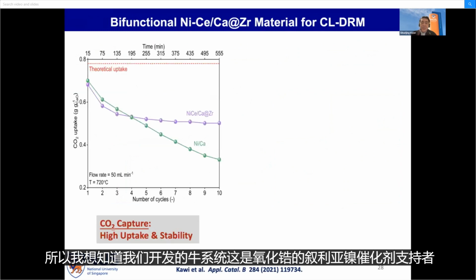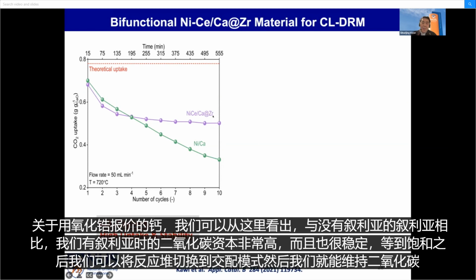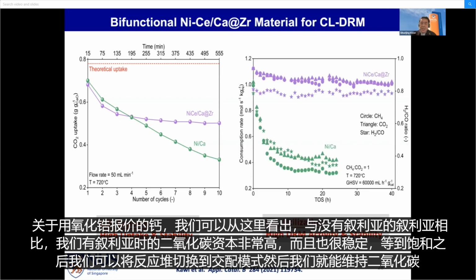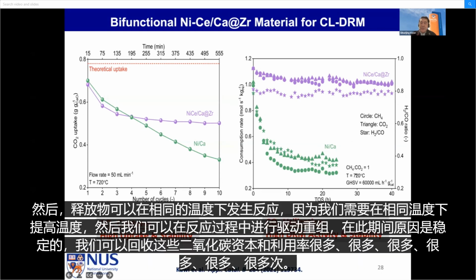So I just showed you one of the catalyst systems that we have developed. This is the nickel ceria catalyst supported on zirconia, on calcium coated with zirconia. And we can see from here that the CO2 capture is very high when we have ceria compared with those without ceria, and it's also quite stable. After it has reached saturation, we can switch the reactor to the methane mode, and the methane and the CO2 that is released can then react. We do need to increase the temperature, and then we can do the dry reforming during the reactions. And the reaction is very stable and we can recycle this CO2 capture and utilization many times.